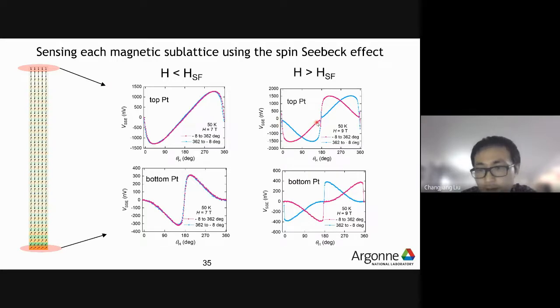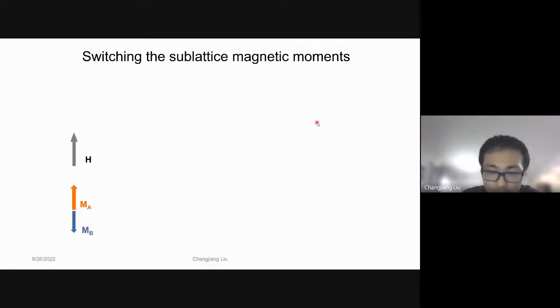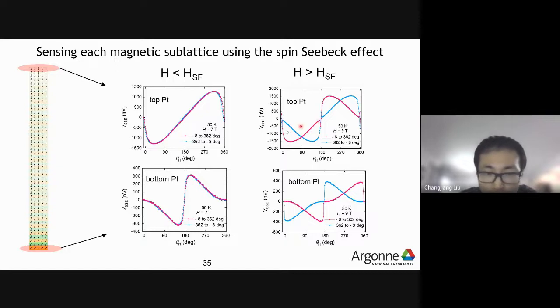You see that the red curve shows this polarity, while the blue curve shows the opposite polarity in the top platinum layer. So now I would like to do one more thing. Suppose initially the bottom surface spin is pointing up and the top surface is pointing down. Now they have opposite polarity. Can I do a manipulation such that I switch the orientation of these two sublattices, so that this response could also be switched, if our explanation is correct?